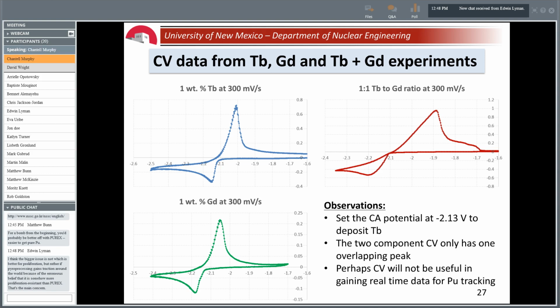And so these aren't taking place at the same time. It's cycling. Obviously they're not at the same time. But I'm struggling a little with the physics of what's going on. In any event, from a practical point of view, one might ask, could you get better distinction if you swept more slowly so that everything is essentially in quasi-equilibrium at each moment? And then one could take that upper right-hand curve and vary the ratio and see if you could see big changes in the structure of the curve. Might be more obvious with a slower speed is what I'm suggesting.